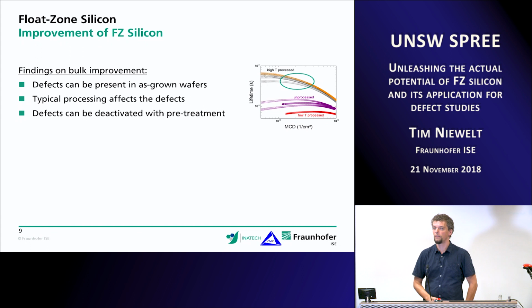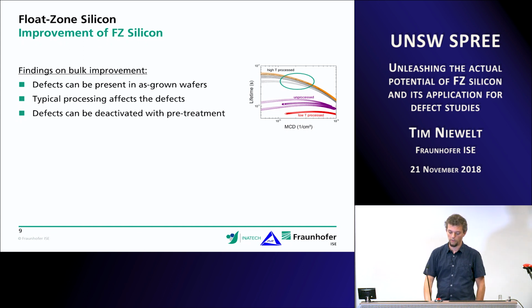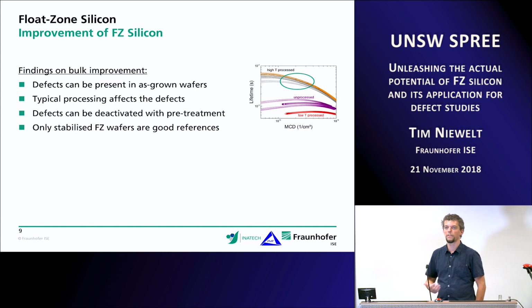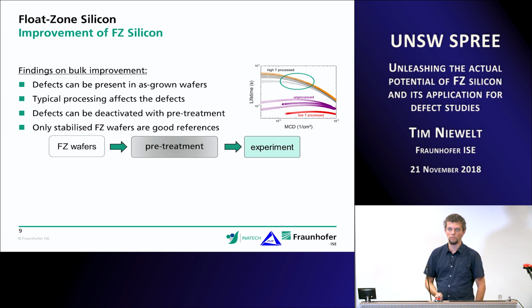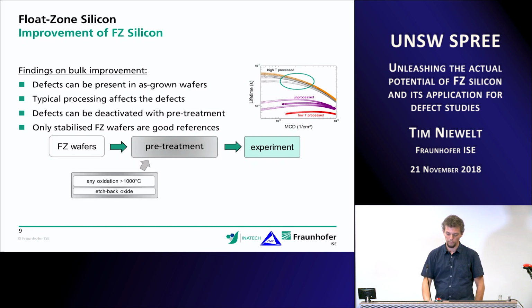The good news is we can deactivate these defects with an appropriate pretreatment, and these wafers then are stable to whatever you do to them afterwards. So once you have done such a pretreatment, you can also go to the temperature range that would otherwise destroy the wafer or the lifetime, and the lifetime will be stable after the treatment. So what I suggest for experiments involving float zone wafers is to always have this pretreatment. How we do it is we do it for the wafers once we've bought them, and then just store them, and when someone wants to have an experiment, we just use treated wafers from the start. A pretreatment that does work is that you just use any oxidation and then etch back everything and then start your experiments.